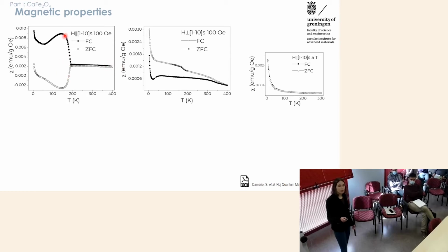And then we observe a maximum of the susceptibility at around 20, under 30 K, which is also where we have this opening in the MH loops. So the behavior macroscopically is quite similar to bulk, but we definitely only see one characteristic Néel temperature magnetic transition. And when we apply the magnetic field perpendicular to the easy axis, we see that this shape is maintained, but much down.